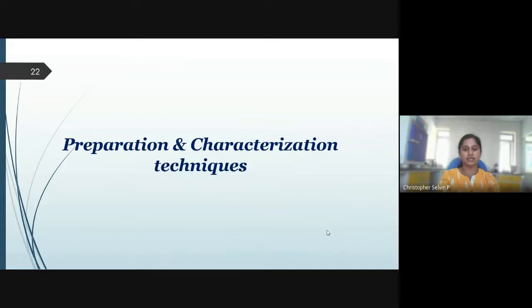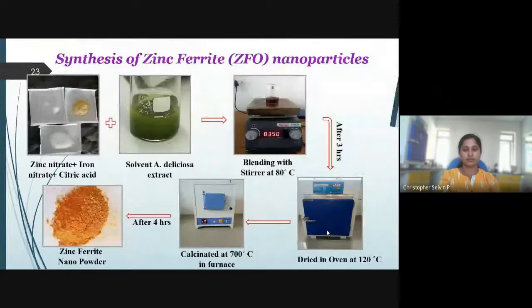Preparation and characterization techniques. In this slide, we are showing the preparation steps involved in preparing the zinc ferrite nanoparticles. Initially, metal salts were taken, and plant extract, to be specific, fruit extract, was prepared. Later, blending of this extract with the metal complexes was made by means of a magnetic stirrer, under continuous stirring for 3 hours at 80 degrees Celsius.